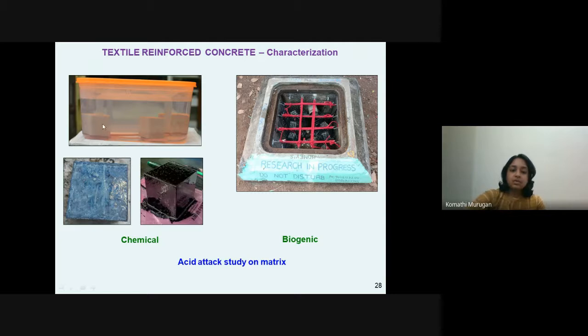The first image shows the pristine concrete cubes of 70 mm size which are exposed to the chemical acids. There are two types of tests that we conduct here. One is the chemical acid attack study, which is conducted in the laboratory, and the second one is the biogenic acid attack study, which is conducted in the real original field conditions itself.